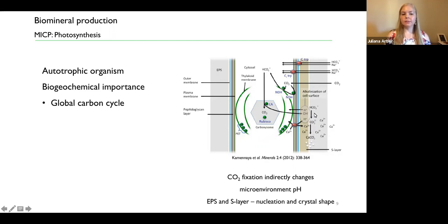What's also known about the photosynthetic process is that both the EPS being produced by the cells and also their S layer have an important feature on the nucleation sites, and also on crystal shapes, depending on the negativity or positivity of the amino acids involved. The challenge with working with photosynthetic organisms is that, as you can see here, there's not a direct enzymatic pathway like there was in the urea degradation, where specific enzymes could be targeted genetically. So that's a little bit of a challenge in this part of the project.